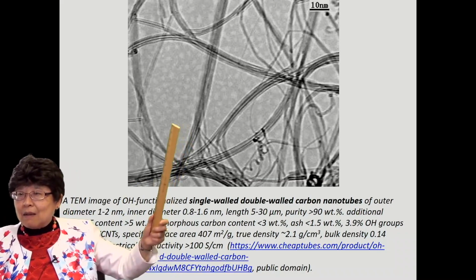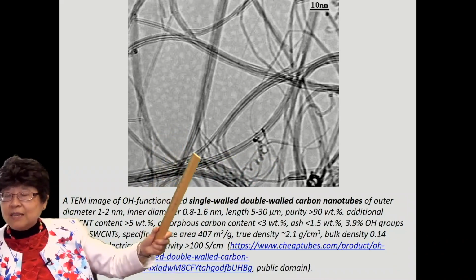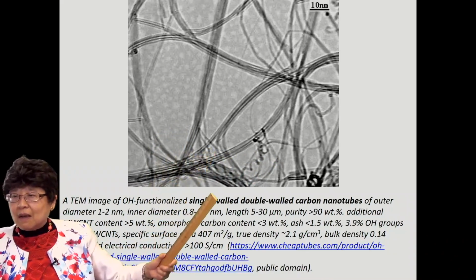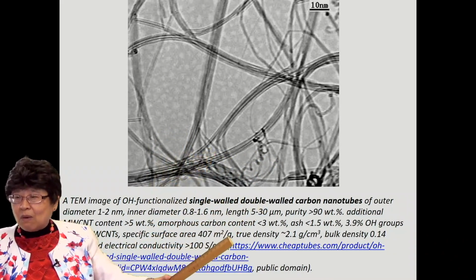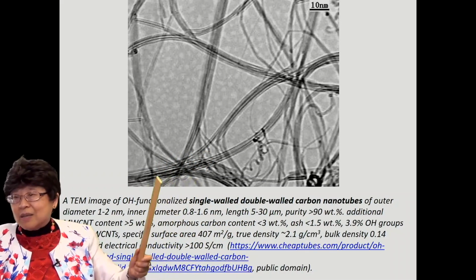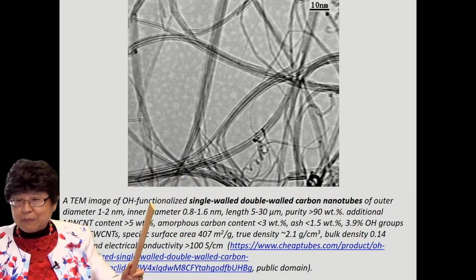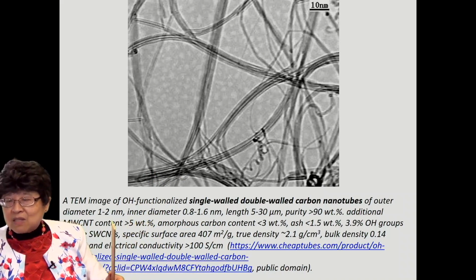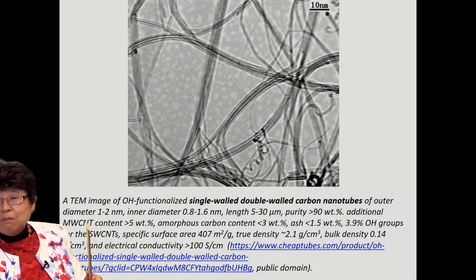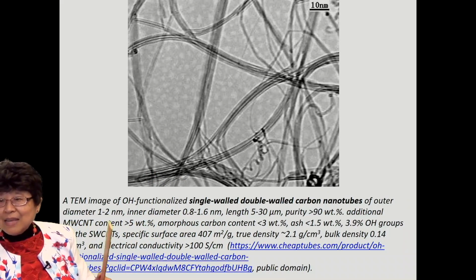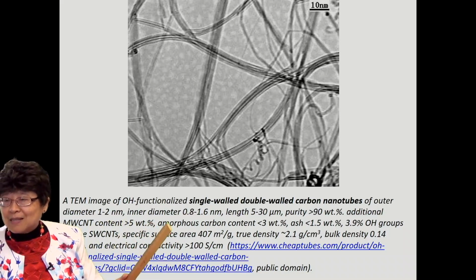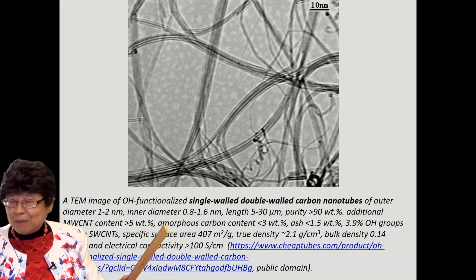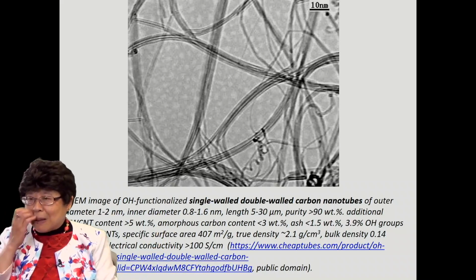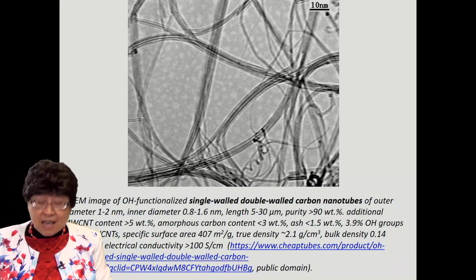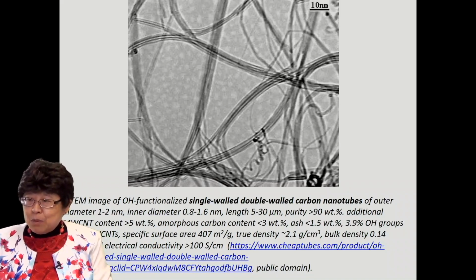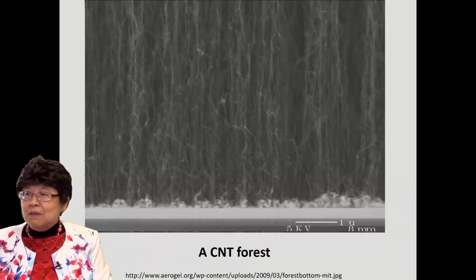This is a carbon nanotube TEM image showing some single wall and some double walled, but in general, it's not purely of one type. In fact, there are some multi-wall that is more than two walls, and even some amorphous carbon, that is a turbostratic carbon there. So one needs purification to get a pure form of carbon nanotube.